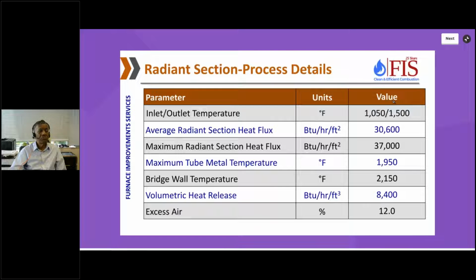This is giving typical parameters. Inlet temperature in the radiant section is around 1050. Flux about 31,000. Maximum flux is 37,000. The ratio between the two is about 1.2. Maximum tube metal temperature is around 1950. Bridge wall temperature, and you can see the bridge wall temperature is the temperature of the flue gas leaving the radiant section, and this is very close, 2150. Volumetric heat release around 8,000. Actually, this looks a lot lower nowadays. They even go to 20,000. Excess air around 12%. So these are the typical parameters of a radiant section for an ethylene cracker.